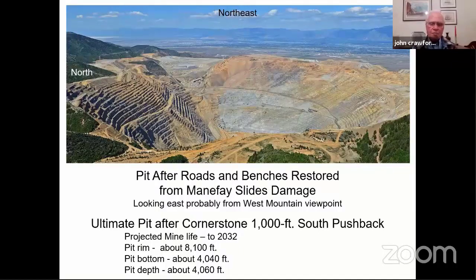So as far as the majority of the production out of here, it is pretty much a conventional sulfide copper ore processing supply chain. They also do have continuing dump leaching, and they have an SX-EW plant, so they are producing cathodes directly here at Bingham from that material, rather than making what they used to call a cement copper, which was high grade and would be sent to the smelter.